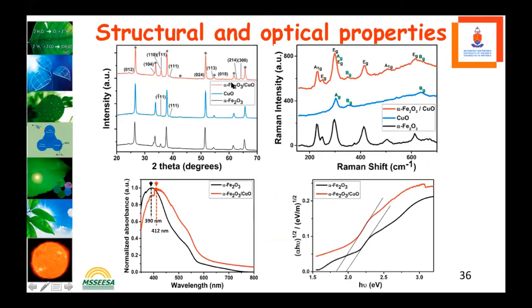But thus far, the XRD results show you that in that heterostructure, you have got pure hematite here, and you have got pure copper oxide here, and we have the heterostructure of copper oxide and hematite in this red curve. And then the Raman spectroscopy measurements are just confirming what XRD has said to us. We always want to do both Raman spectroscopy and XRD.